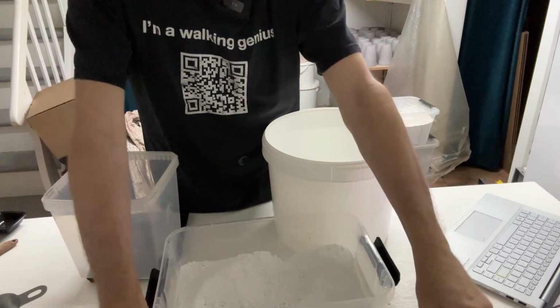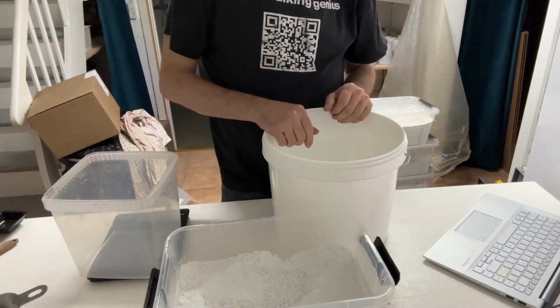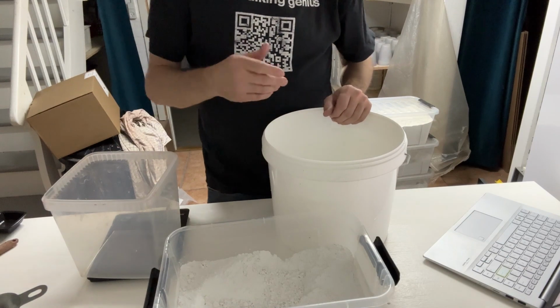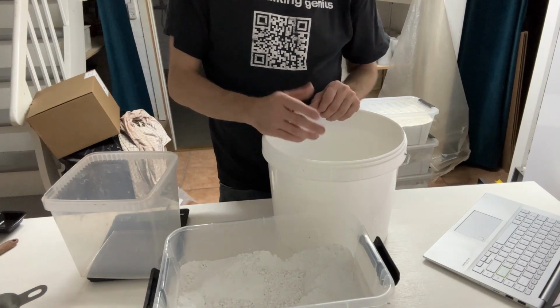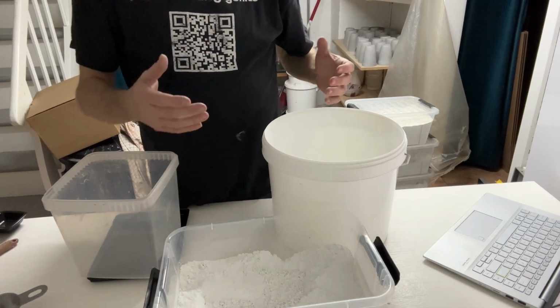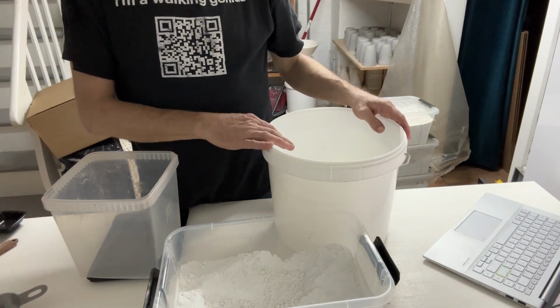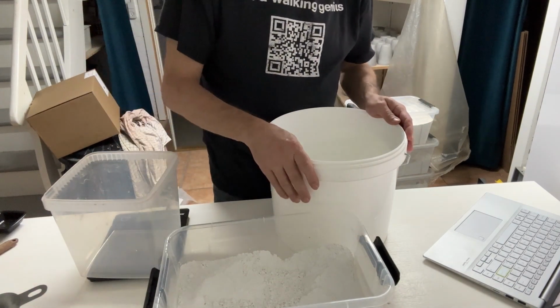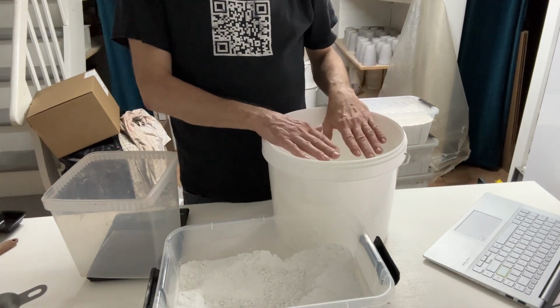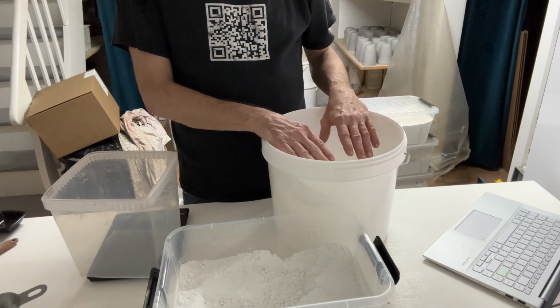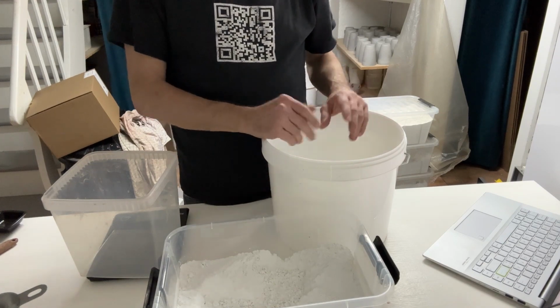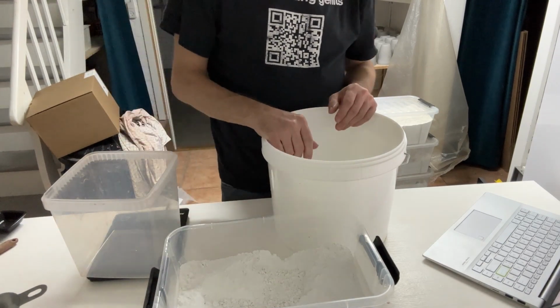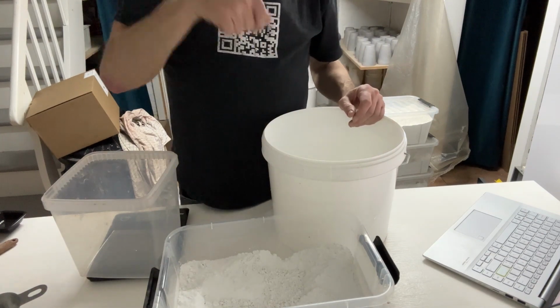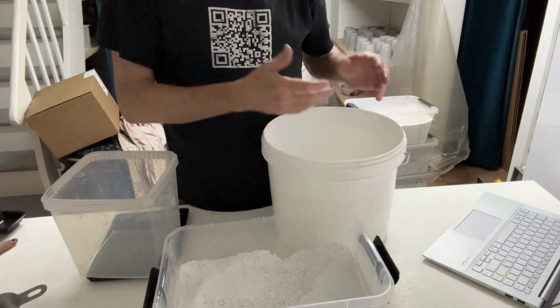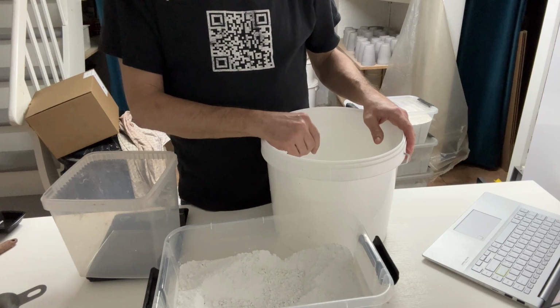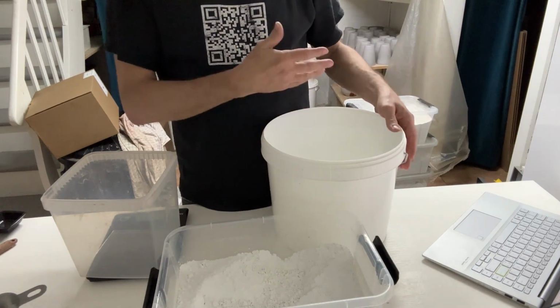Now I already calculated, because the recipe says 48%, so I'm gonna mix up 4,000 grams of dry material. I like to mix up, even though it's a glaze I haven't tried before, it could be completely bad, but I will mix up 4 kilos of dry material, and with the added water that should be maybe about 7-8 liters or something. The reason is I like to dip most of my pots, and you need to have enough glaze for that. And also, worst case, I can throw it out.